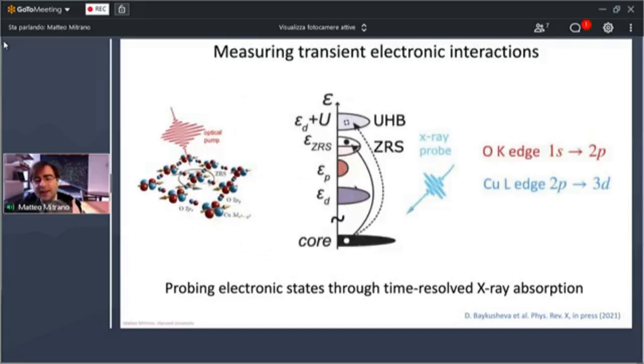So this tells you, when you start plotting the density of states close to the Fermi level, you have essentially the d orbitals that tend to split because there is correlation. You have to pay an energy cost of order U for putting two electrons on the same site. This is Coulomb repulsion. And then we have the p orbitals that lie in between the d orbitals, the so-called lower and upper Hubbard band. And then we have one hybridized state here in the middle. And when you start doping it, the Fermi level falls in the Zhang-Rice singlet.